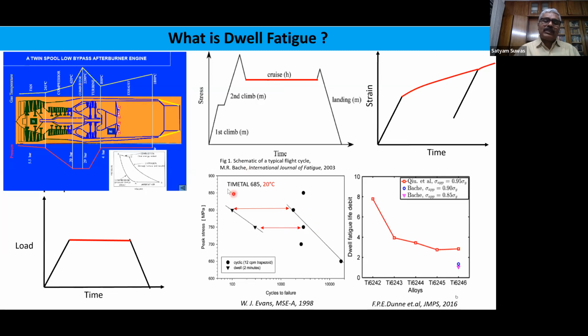First, it was reported in IMI 685, which is the IMI titanium designation. And this is observed at 20 degrees Celsius. That means at ambient temperature. And one main reason attributed to this is room temperature creep in the system.